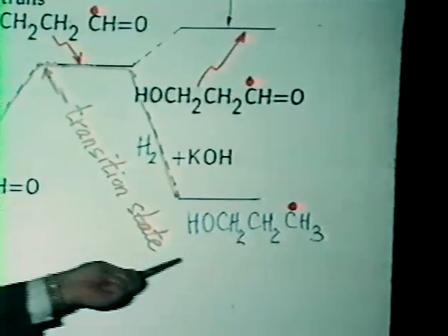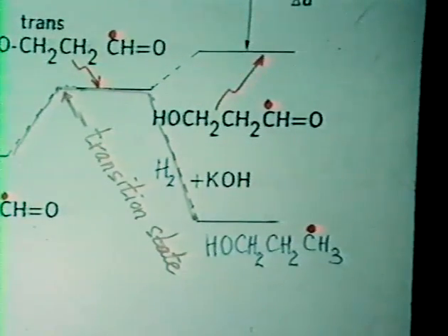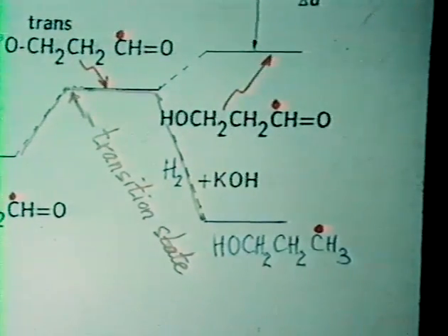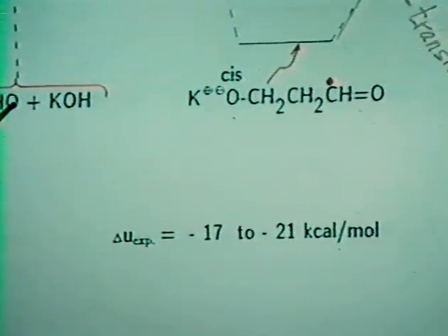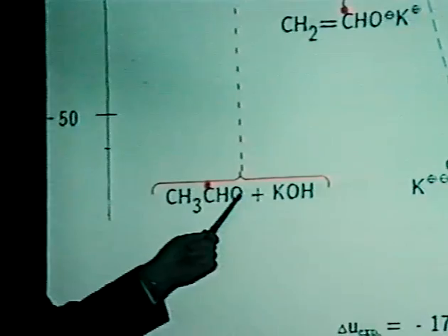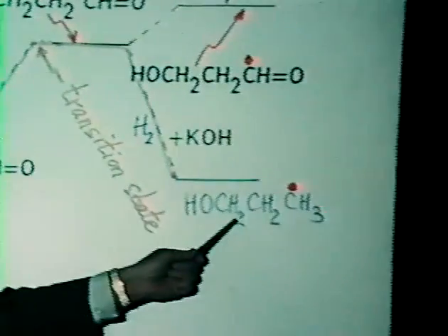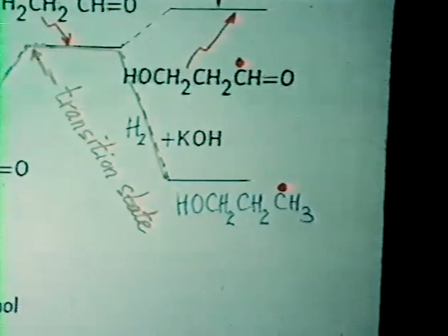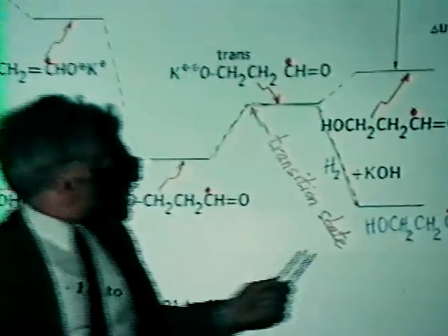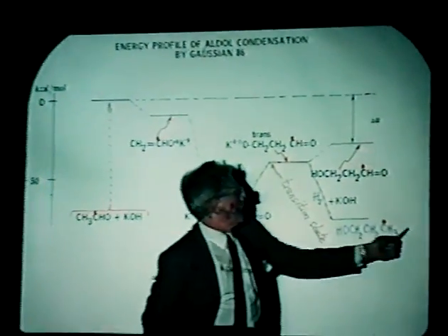Then we hydrogenate this end here to produce the linear propanol of the isotopic composition that the experiment directed us to. In other words, specifically, this reaction cycle rejects the oxygen of the injected ethanol and retains specifically the oxygen of the added C1 intermediate. We call this, because the expectation of the aldol synthesis is that this OH group or CO group should be here, the aldol coupling with oxygen retention reversal. We gave it this name and the journals accepted it.